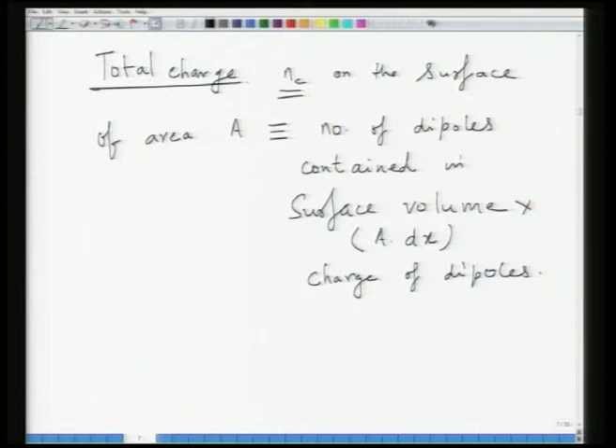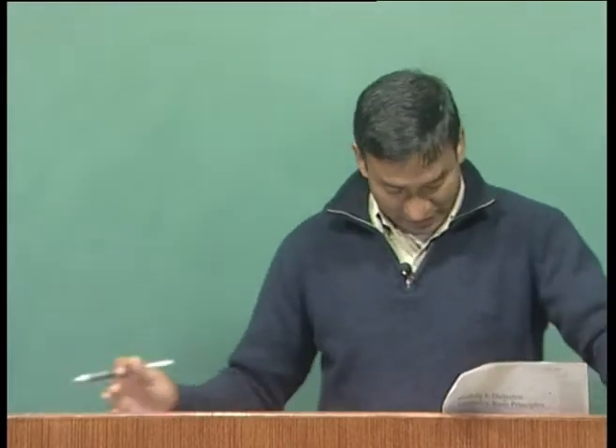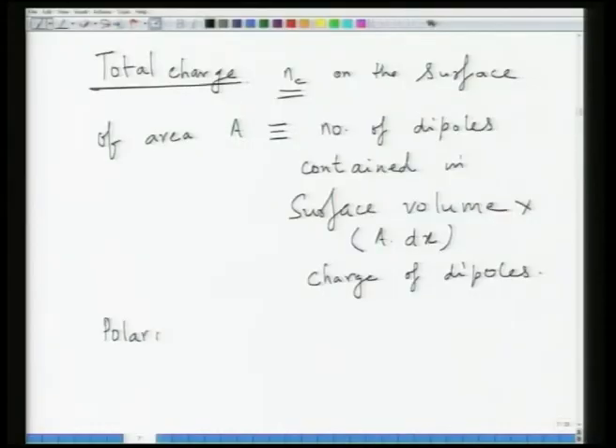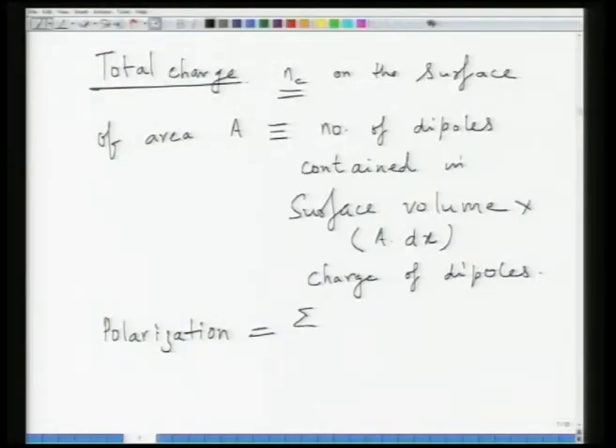So, now what is this? This is nothing but equivalent to one layer of surface charge on the surface of the capacitor. So, assume that we have this homogeneous distribution of dipoles on the surface, we can calculate the total polarization. Now assuming that they are homogeneously distributed, the total polarization will be nothing but total dipole moment divided by the volume. So, basically sigma mu s, the sum of all the surface dipole moments, divided by Vs.